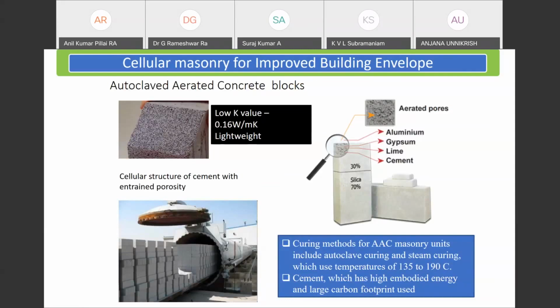These AAC blocks are conventionally made with cement binder. So we use cement, and in the cement binder, air bubbles are introduced, and then they are cured in an autoclave. Now we are using the same process of autoclaving, except the base material we are using is an alkali-activated fly ash, derived completely from fly ash, and we are able to produce the same AAC, except they are now AAG, because they are autoclaved aerated geopolymer blocks, which have very low thermal conductivity for use as non-structural masonry.